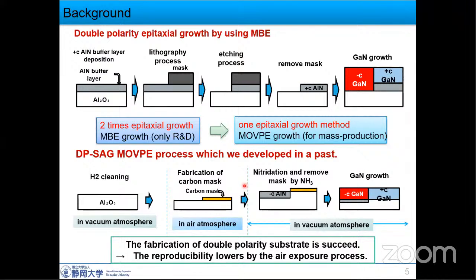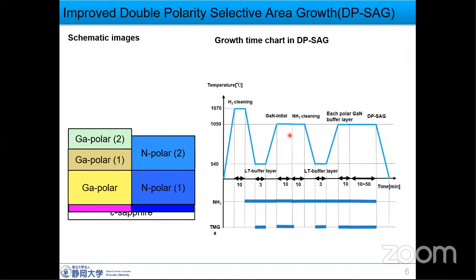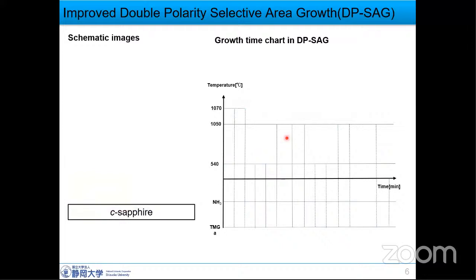However, the reproducibility is low because of the air exposure process. Therefore, we made further improvements and built the improved DP-SAG process. In this slide, I explain our improved DP-SAG process. First, a carbon mask was patterned on a c-plane sapphire. Then we put the sample in the chamber, and the temperature was raised. Hydrogen cleaning was treated for gallium polar gallium nitride on the unmasked region.